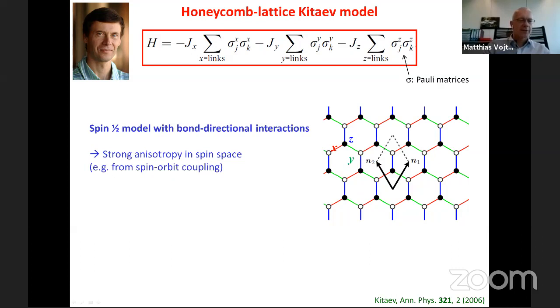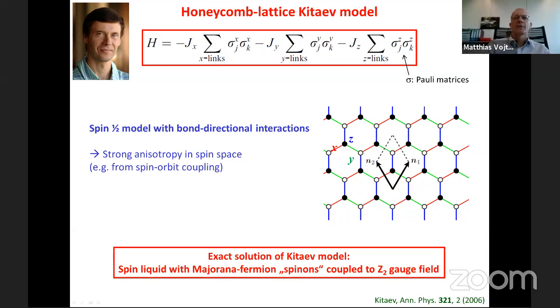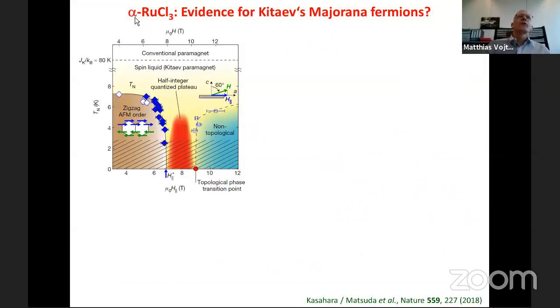That's one of the very rare cases where you can do this in 2 dimensions. And this exact solution shows that this model realizes a spin liquid. And this spin liquid has Majorana fermion excitations. So these are the spinons, which I mentioned before, which are coupled to a static Z2 gauge field. Now, this theory proposal has triggered tremendous activities in the search for materials which realize this. And one of the best candidates by now is a material called ruthenium chloride. And I just want to highlight one recent experimental result here.